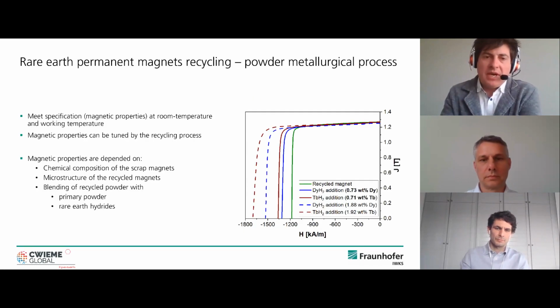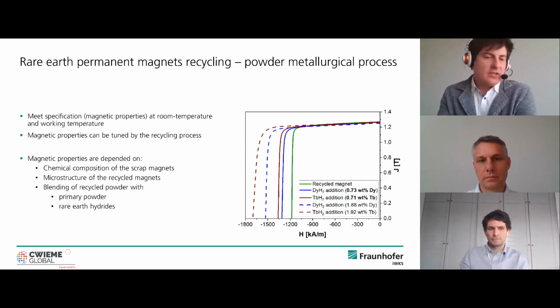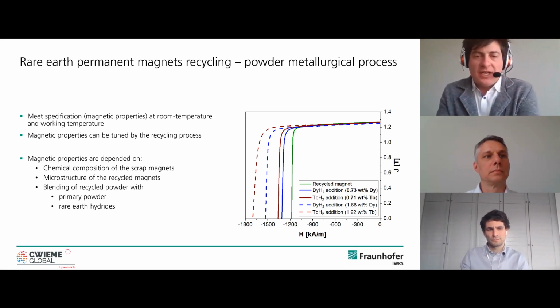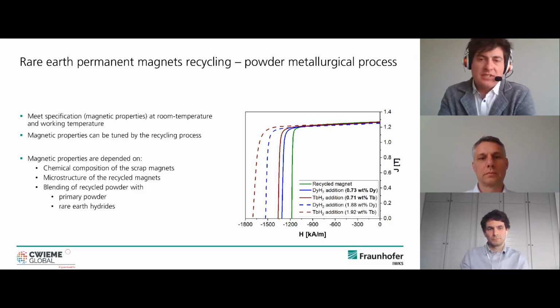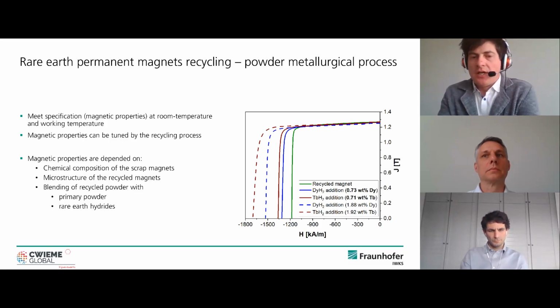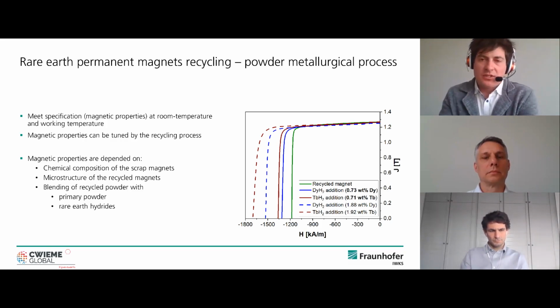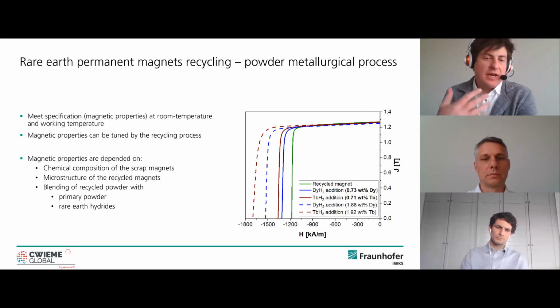When you make a magnet out of that, you have different kinds of possibilities. So basically, our goal is to meet the specification of the customer, and a magnet is defined by 3 important dimensions. So one is remanence, on the y-axis. You want to have a high remanence, the highest remanence possible, basically, because then you can have a huge magnetic moment. On the x-axis, the coercivity, you want also to have a high coercivity because it will protect the magnet from demagnetization, which can happen at higher temperature.